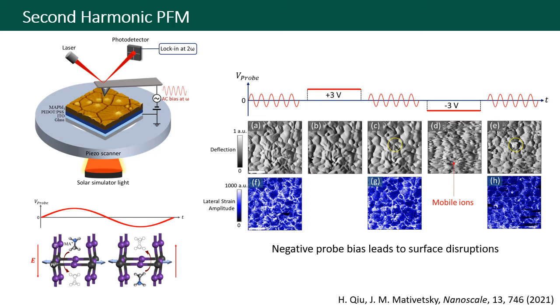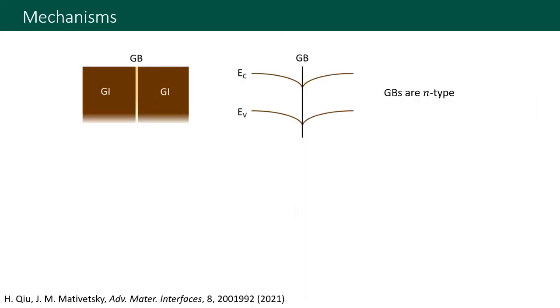However, if we apply a negative DC bias to the probe, the positively charged mobile cations will be attracted to the sample surface, and that leads to a streaky appearance in the image. Subsequent imaging shows also that new protrusions form at the surface of the sample as a result of this cation accumulation. These signatures of cation motion and nanoscale degradation are only observed under combined stimulation with light and voltage, with the light acting to soften the perovskite lattice and facilitate ionic motion.